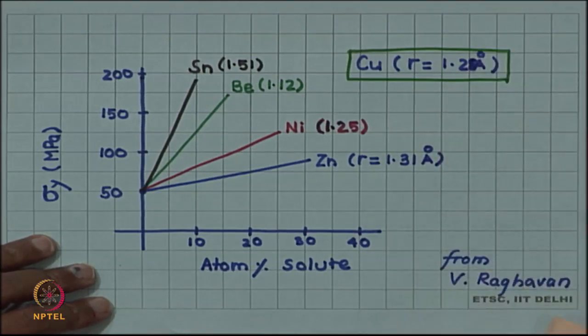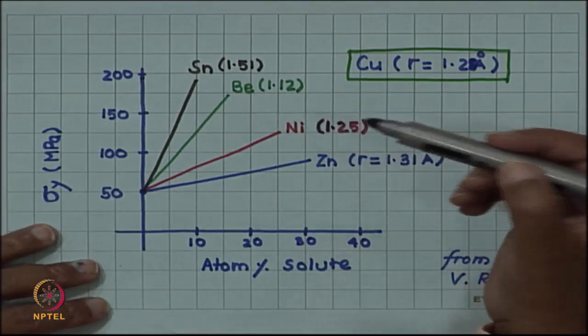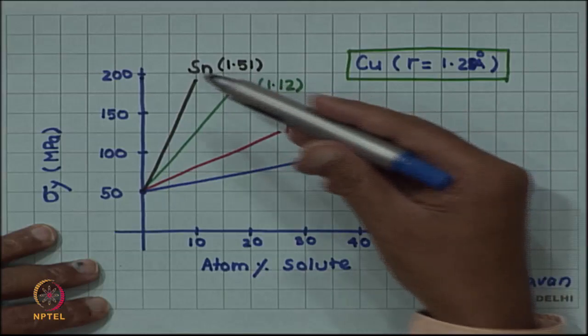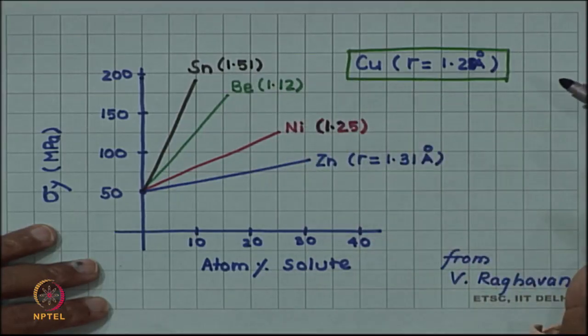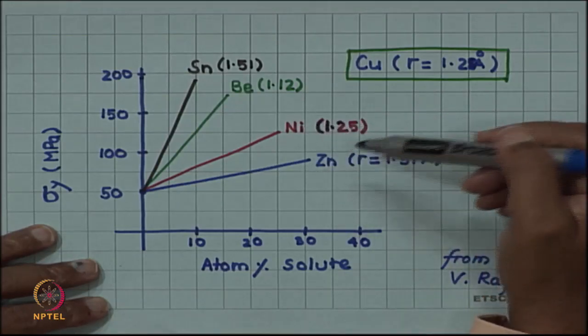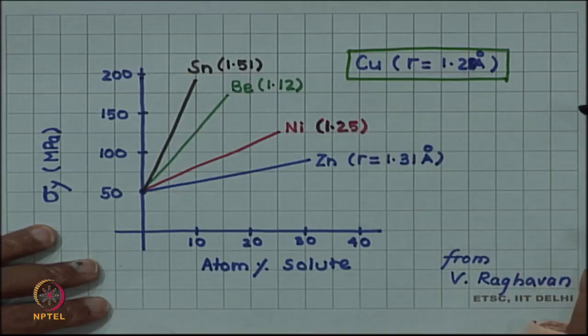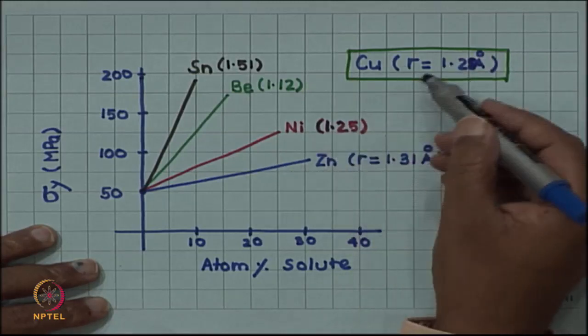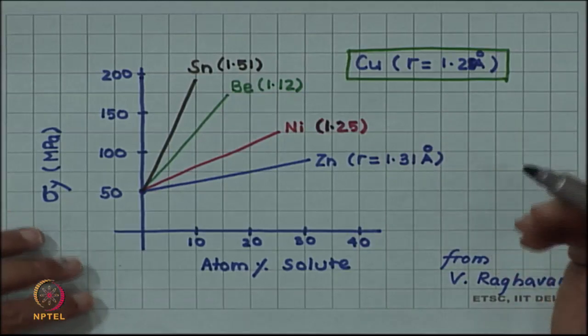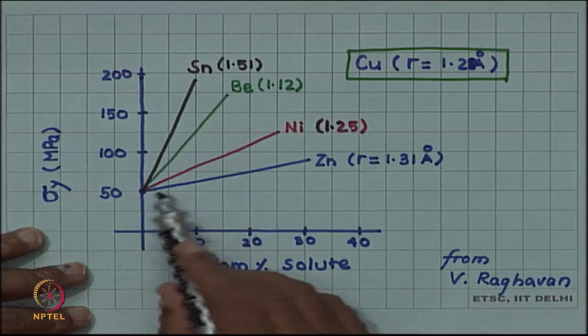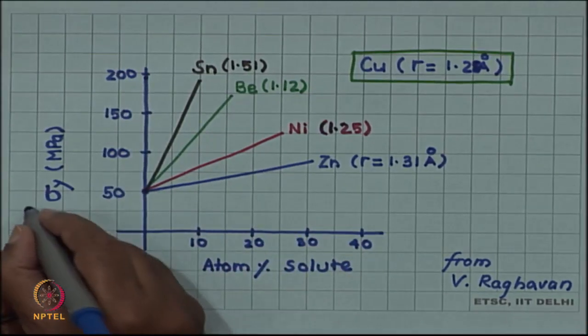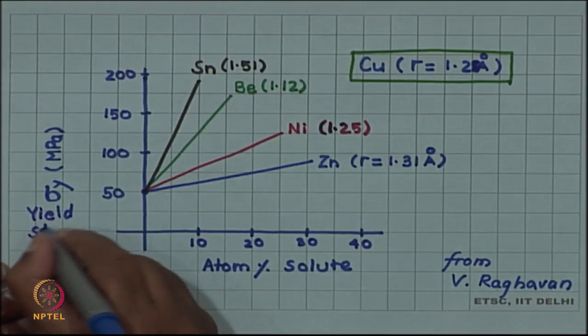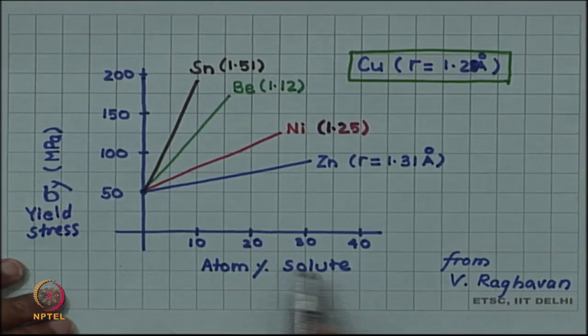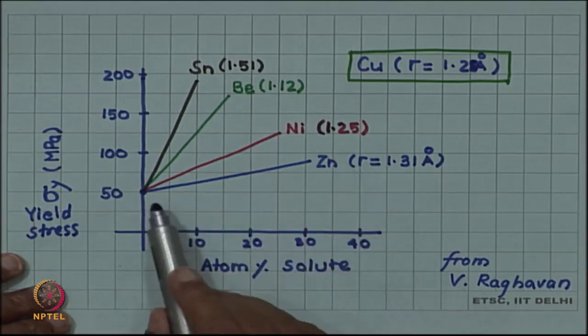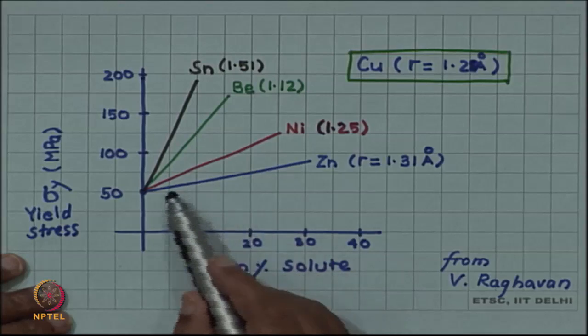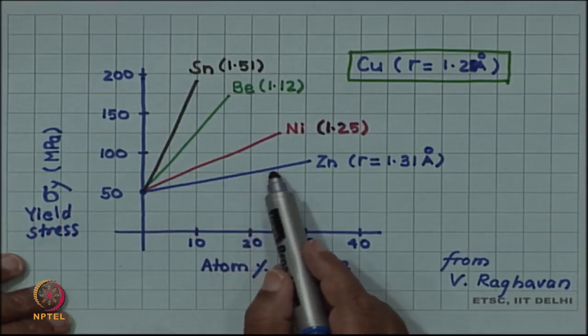This is 1.28 angstrom, and in that we use as substitutional solute different elements, zinc, nickel, beryllium and tin, and they have their own radii. You can see nickel and zinc both have radii close to the radius of copper. So, since their radii are matching, the strain created by them is small. So, the effective straining is less. In this plot, we are plotting the yield stress sigma y as the y axis and atom percent solute as the x axis. So, for any given solute, let us say zinc, if I am adding zinc to copper, as I increase the solute concentration, yield stress is increasing.